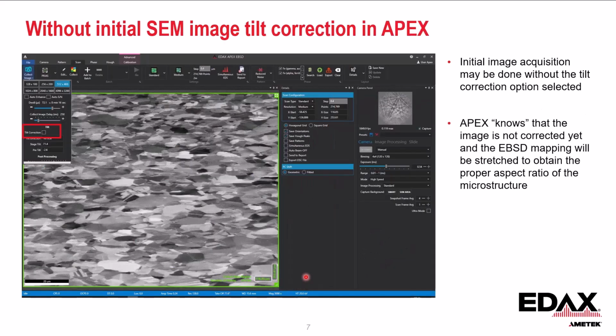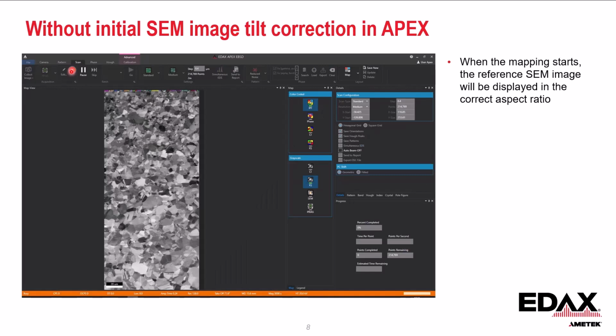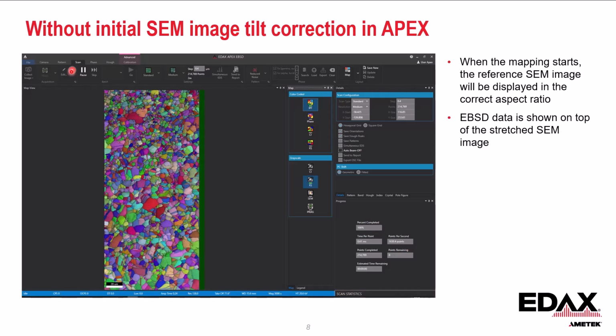You can also collect a map without tilt correction. You can simply take away this check mark. It doesn't mean that now your measurement will be distorted, because Apex knows that the image is not corrected yet, and when you start your measurement, the image will be stretched to show the proper aspect ratio. So when I do that, I hit the collect button over here, and then the image gets stretched to the proper aspect ratio, and you can see this is about 3 times larger than the field of view we saw earlier. So it allows you to get a much larger mapping area. And then on this image is where we collect our EBSD data, and we get again a good tilt corrected image that has the proper aspect ratio of the microstructure.